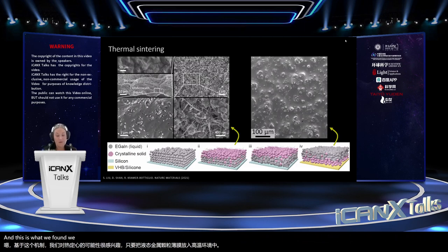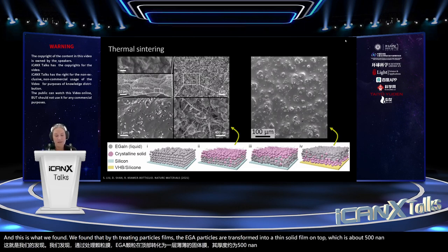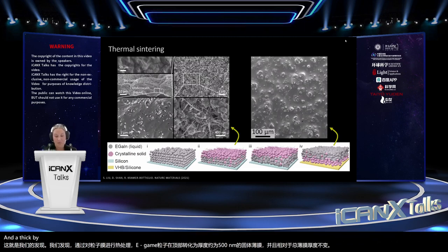We found that by thermally treating particle films, the EGaIn particles are transformed into a thin solid film on top, which is about 500 nanometers thick and invariant with respect to the total film thickness, and a thick biphasic portion with solid particles embedded in liquid EGaIn.